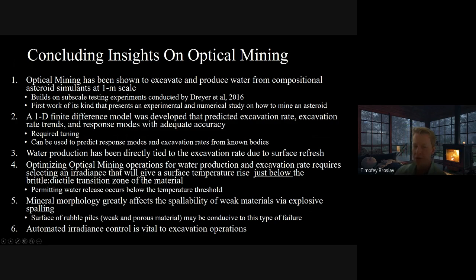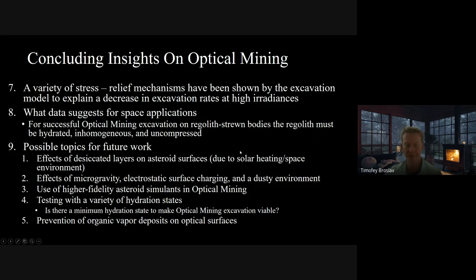Furthermore, automated irradiance control is vital to excavation operations, as has been shown in how very, very high irradiance can significantly decrease your excavation rates. And so you must be able to normally have your beam irradiance at one level, at your optimal irradiance level. Next, a variety of stress relief mechanisms have been shown by the excavation model to explain the decrease in excavation rates at high irradiances, and these were the surface relief conditions, the brittle to ductile transition, and the melt formations that I included in the model.